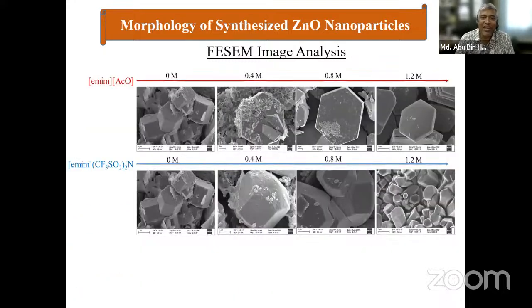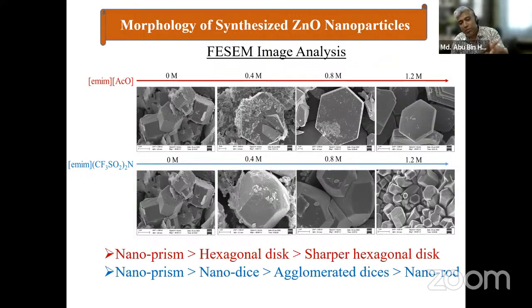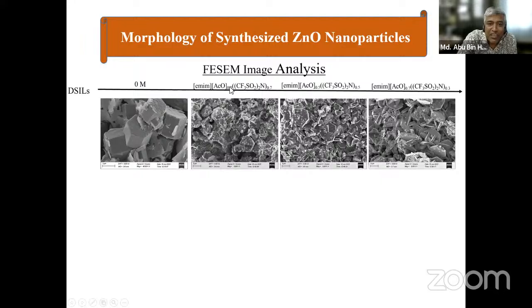Now let us move to the field emission scanning electron microscopic image analysis. And here is the beauty actually. You can see that this is a single ionic liquid from 0 molar to 1.2 molar. We have checked the field emission images. You can see here the structure is being changed for both the bis(trifluoromethanesulfonyl)imide and acetate anions. In the first scheme, it shows nanoprism, hexagonal disc, and that gradually moves to a sharper hexagonal disc-like structure. And here from nanoprism, nano discs, agglomerated discs, and finally you can see some rod-like structure here. And when we used double salt ionic liquids, here is 0 molar, that means none. And here we have 0.3, 0.7, here 0.5, 0.5, and here 0.7, 0.3.